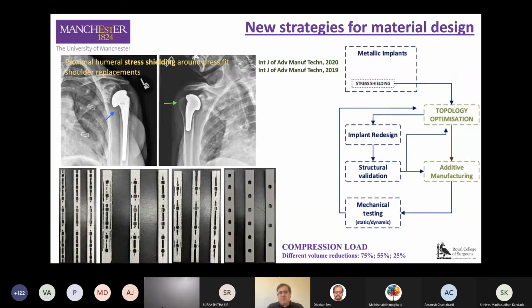So, as you know, most of the bone plates are made in stainless steel or titanium alloys. Some can be chromium cobalt. But the major issue is that the mechanical properties of these plates are quite high compared to the mechanical properties of bone. And as a consequence, we have a problem called stress shielding. So we observe after a certain period of time that there is some bone loss in the vicinity of the implant. So we decided to use topology optimization to redesign these plates, considering different physiological loads and also different values of volume reduction.